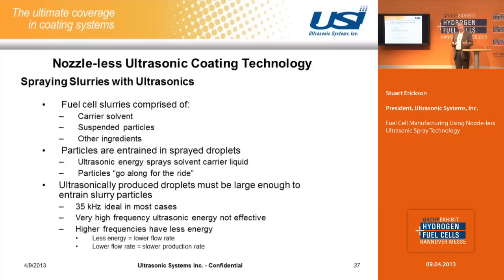One important fact for ultrasonic spraying is that what we're doing is we're spraying the carrier solvent, and the particles go along for the ride inside the drops. So depending upon the particle size, which typically the maximum particle size is up in the double-digit micron size, when you're spraying it, the particles are in the drops going along for the ride. Typically we use 35 kilohertz, which is a very good basic frequency for producing the right size drops, and is also producing the right flow rate range. If we go to higher frequencies, we limit our energy, we limit the drop size, and therefore we limit the amount that we can spray, or even the particle size that we can spray.